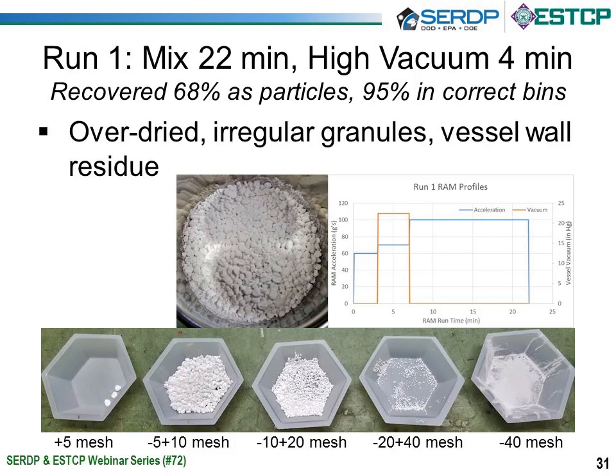In the small-scale runs, we did three runs where we altered the total mix time, the amount of time that we apply a high vacuum, and the amount of time that we apply a very high G-force for the polishing and rounding of the material. In run one, we did a total mix of 22 minutes. For all runs, we have an initial period with no vacuum and 60 G mixing force in order to wet the material with the lacquer. After that first initial 3 minutes of wetting, we then apply a full vacuum. In run one, we applied a full vacuum for 4 minutes, and we upped the mixing force to 70 Gs. After that 4 minutes, we turned off the vacuum, and we increased the mixing force to 100 Gs for the remainder of that mixing cycle.